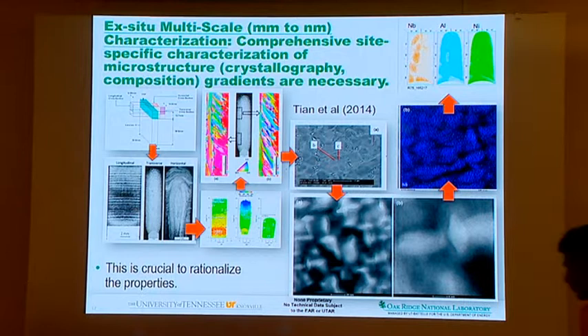There was a lot of in-depth analysis done with the transmission electron microscope. I'm really happy you have a TEM around the corner. You can do the same thing here. And then we can look at the atomic level with atom probe. If you want to do that, you can go to IIT Madras or IISc. You can get that kind of information too. So this shows how the microstructure is evolving, but we cannot do this comprehensively for an additive manufactured component because it's too expensive. Each one is around $1,000, which becomes totally exorbitant for a comprehensive measurement. But you can use this information to validate computational models.